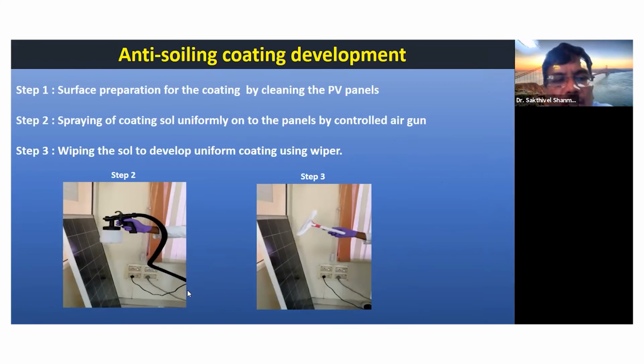This is a very simple process technique. You can see the panel size is around 1 meter by 2 meter. So if you want to apply this coating in the field, the coating should be curable at ambient condition. That is another important requirement. So we have successfully developed a coating formulation suitable for curing at ambient condition, with high transmission, high hydrophobic property, as well as high weather stability, withstanding the IEC standard.